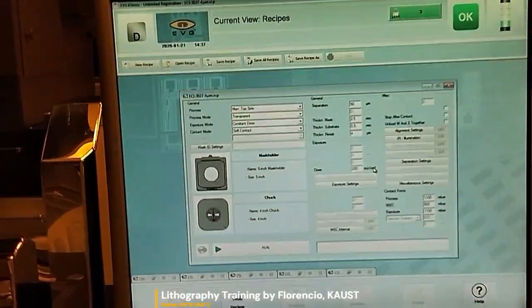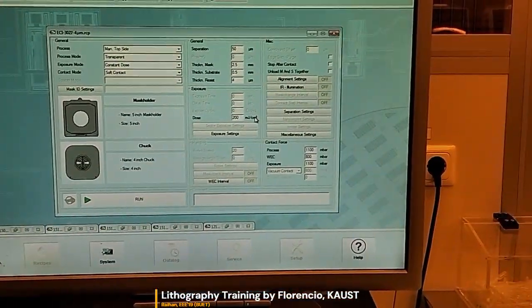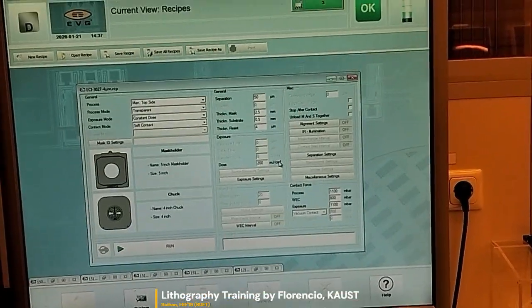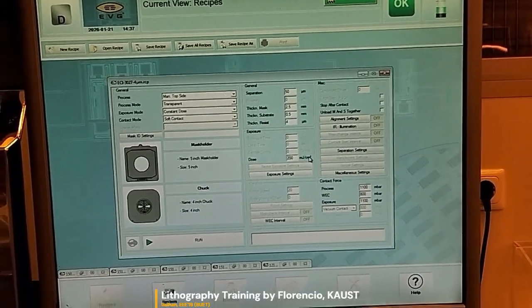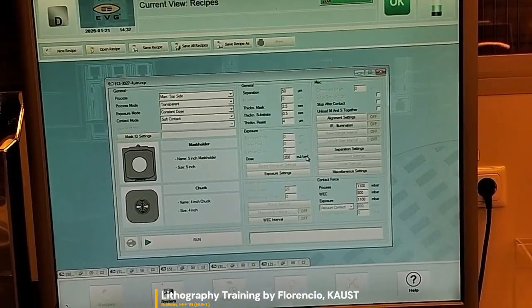So there are two defects here. It's either overexposed or underexposed. So don't overexpose, because sometimes your CD is affected because you are exposing sides that are not supposed to be exposed. And when you expose, remember, positive you remove, then this will collapse. But if it's negative, you expose the part you don't need, it will expand. So your tolerance will be bigger or smaller.